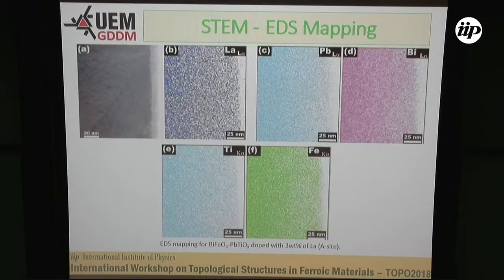We did EDS mapping for these regions, and you see for each of the atoms that we have in our chemical formula, we have no concentrations of atoms in these stripes. It's an indication that our sample is very uniform. Chemically speaking, it's a very uniform sample that has no clusters of different atoms or a concentration of one kind of atom in this stripe. For example, it's not only lanthanum or only lead and so on. It's a good result because we see that our sample is chemically homogeneous.